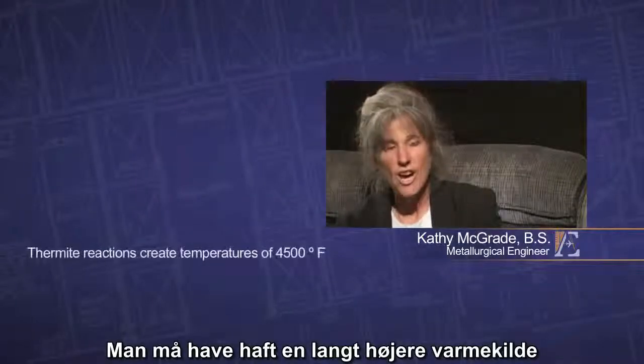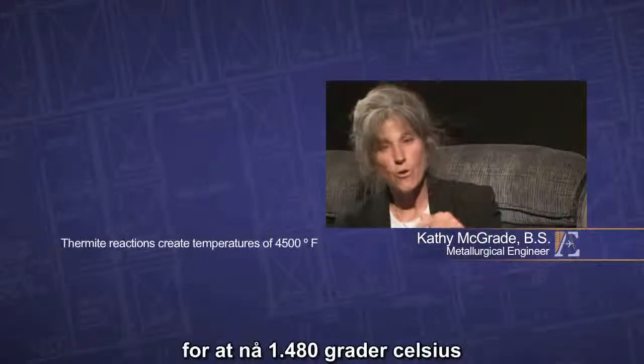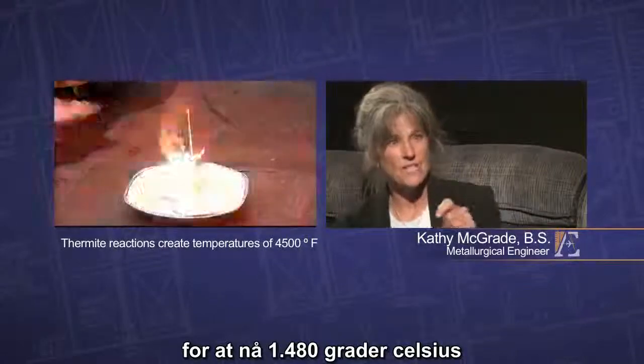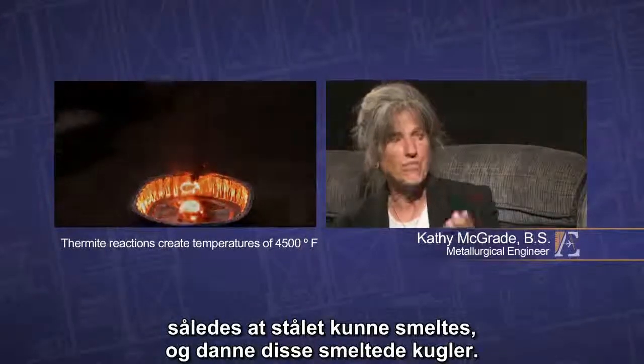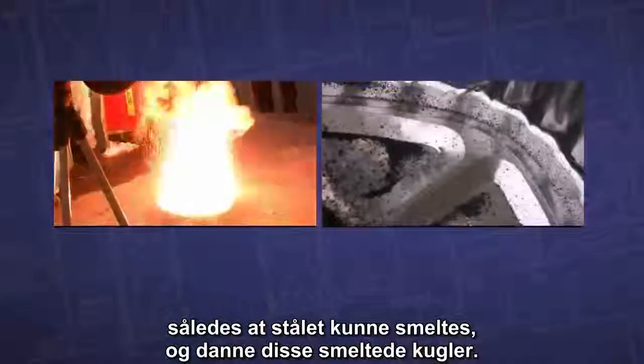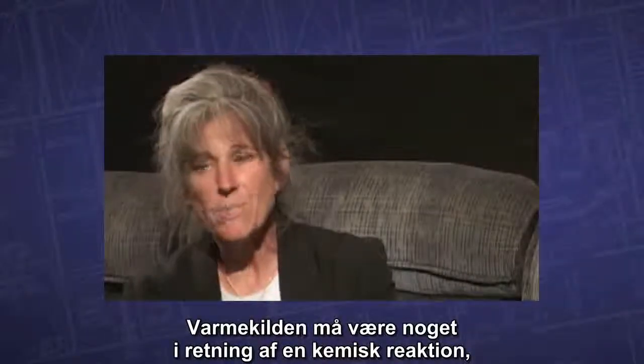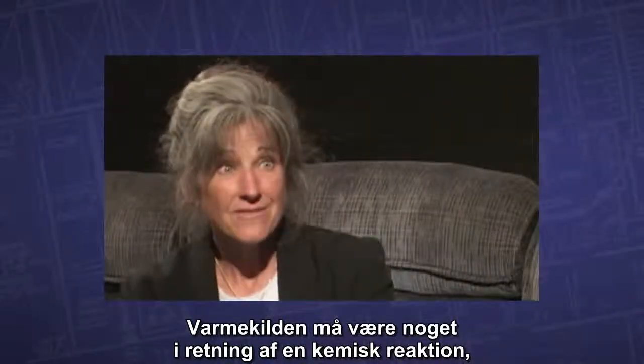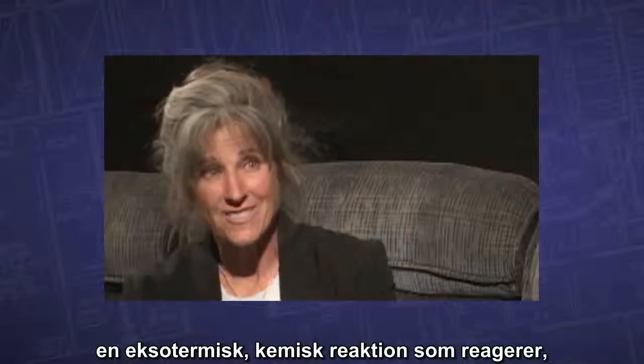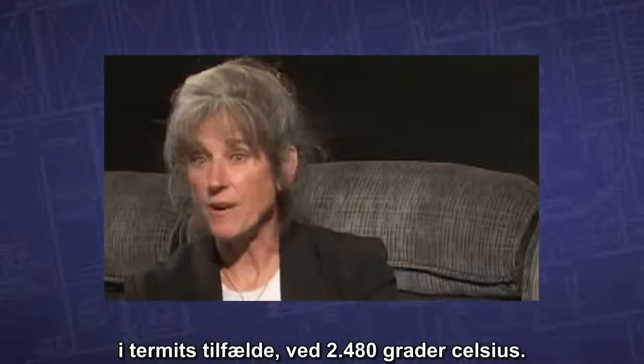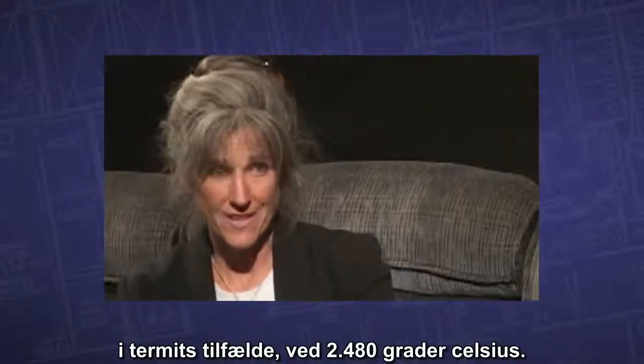You must have had a much hotter heat source for you to get 2,700 degrees Fahrenheit in order to melt the iron to get these molten spheres. Your heat source must be something like a chemical reaction, an exothermic chemical reaction that reacts, in the case of thermite, at 4,500 degrees Fahrenheit.